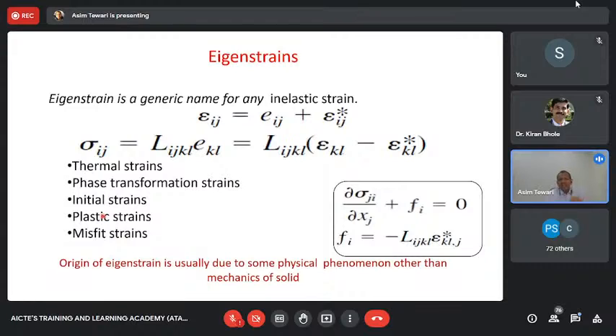So what you realize is that the strain which you had, which we called eigenstrain, needs to be subtracted from the total strain. Total strain is made up of two parts, eigenstrain and elastic strain. What we just saw was an eigenstrain, a strain because of inelastic region, which was expansion because of heating. Since there was no constraint, the material was allowed to expand freely, which means the total strain was equal to the eigenstrain, which means the elastic strain was zero. And stress is not related to strain, but stress is related to elastic strain.